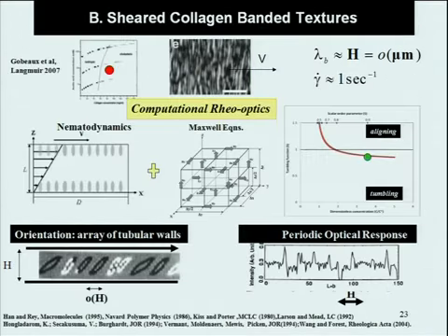So now we have collagen should predict band formation. So this is what is observed. The collagen, the sheared collagen solution at low shear rates in a gap in shear cells in the micron range give you nice pattern formation bands, as you expect, perpendicular to the flow direction, of a characteristic length scale, which scales with the gap thickness. And this we did with the whole nematodynamics and solved for the Maxwell equations and computed the optical response and fit very nicely the optical response with the optical bands. These bands are observed between cross polars. So you see these bands perpendicular to the flow direction.